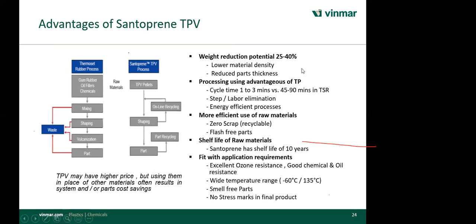You can reduce the weight by 25 to 40% when you convert from the TSR, thermoset rubber, to the TPV. The cycle time of the TPV is 1 to 3 minutes compared to a minimum of 45 to 90 minutes in case of a rubber article. You can eliminate labor. Only one person is enough to handle your shop floor, from the product filling to your machine to the end level.